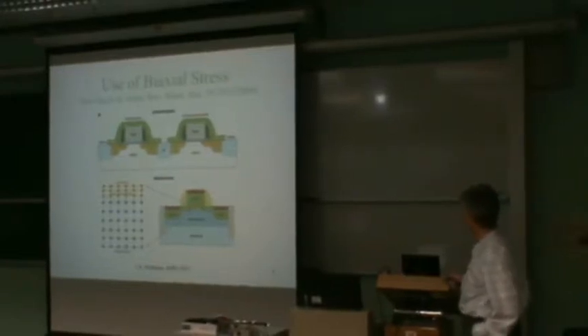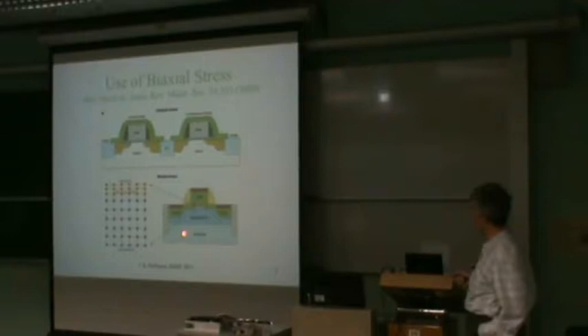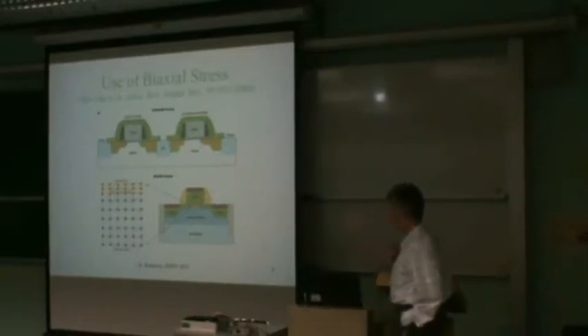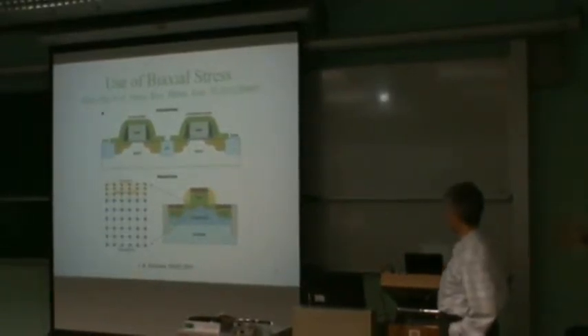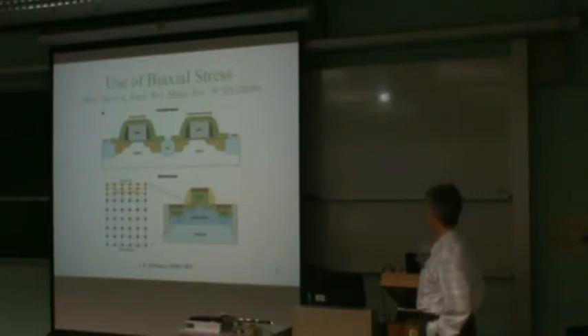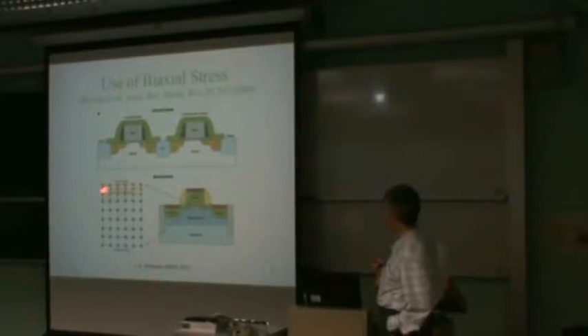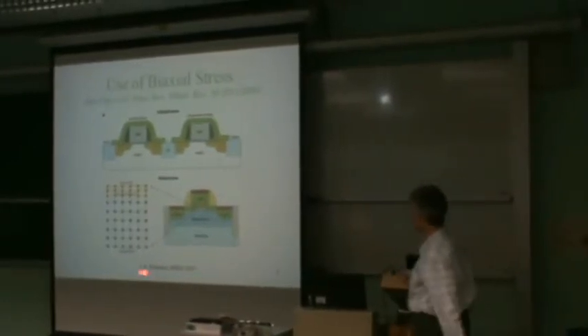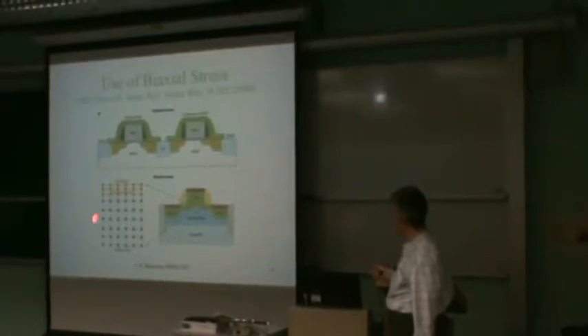This is looking at the questions, a different review article, again showing some of the configurations that are involved. None of these is labeled with the dimensions, but we are talking about getting in the 22 nanometer technology, we're talking about getting channel lengths of the order of 20 nanometers, and this is where the gate starts to become a problem. But there is also the question of whether it's better to use biaxial stress by using an epitaxial layer that would be grown in here, or one of the methods, for example, that's illustrated here to get tensile stress is to use a buffer layer of silicon germanium and then grow the silicon on top of it